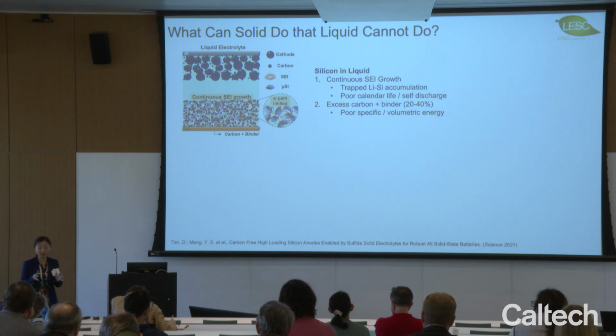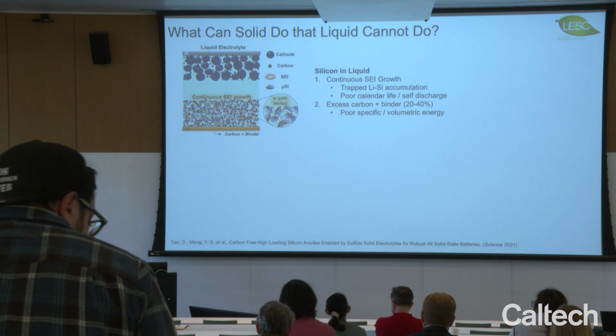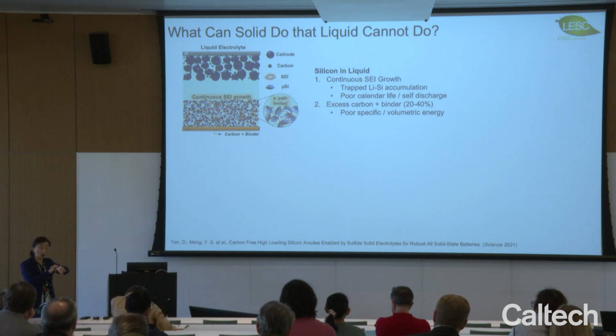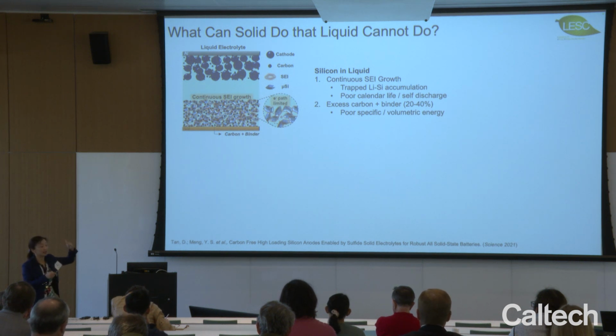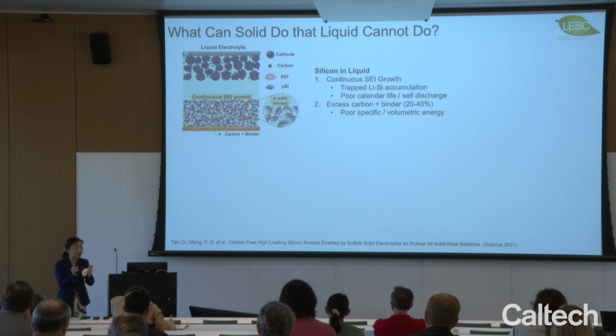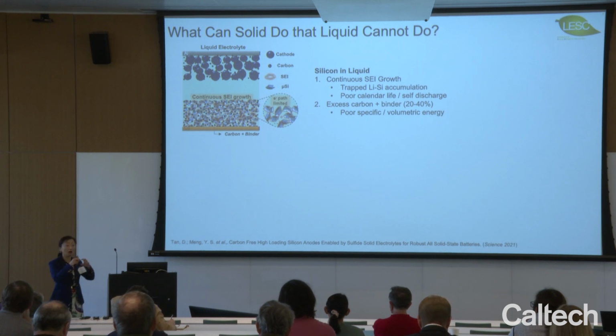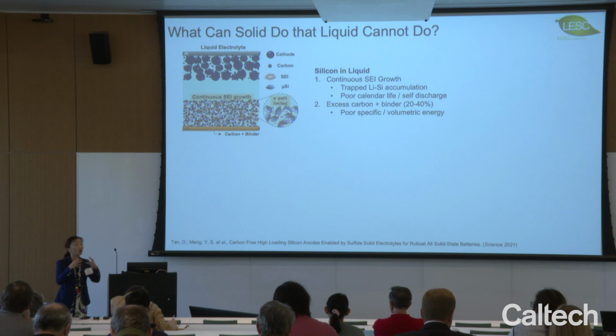So since 2006 until today, 18 years have passed. Silicon loading in a smartwatch is about 5 weight%. So they add very little to improve the energy density a little bit, but because of this challenge, silicon could not make it into the electric cars because nobody wants to risk having a 5% energy increase, but then risking the cycle life degradation, because each of those volume expansion and shrinking will cause the degradation and the cycle life degradation.